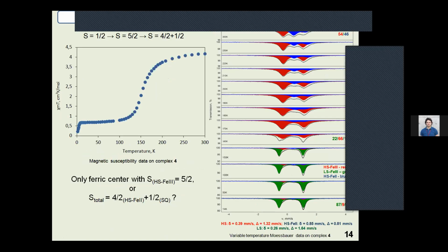In the case of compound 4, it is more substantial due to the higher percent of molecules in the high spin state at this temperature, about 13%. It means that the plateau is located at higher magnetic susceptibility, and we observe a sharper decrease due to the bigger concentration of high-spin molecules. As I said, in most cases I saw it explained by the hyperfine splitting. Zero field splitting, I'm sorry. Zero field splitting. Yes. Thank you.